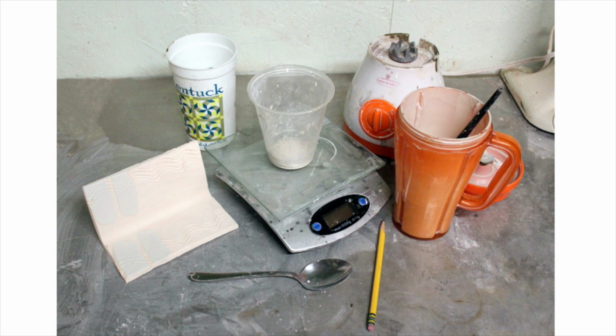Then mix up the base glaze to be tested. I like to mix up a 200-gram batch for better accuracy using a small blender. Brush on a stripe of the base glaze on the far left side. Next, add a particular amount, for example 10%, of the influence ingredient to be tested into the base glaze, mix thoroughly, and make a stripe of that mixture.